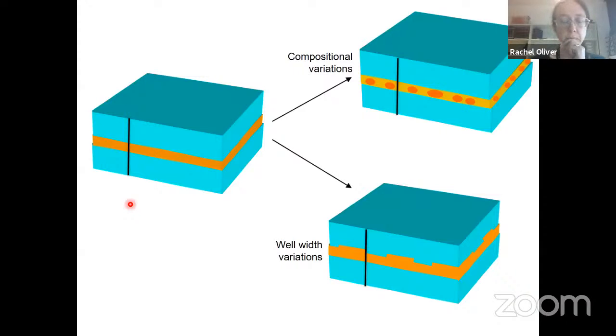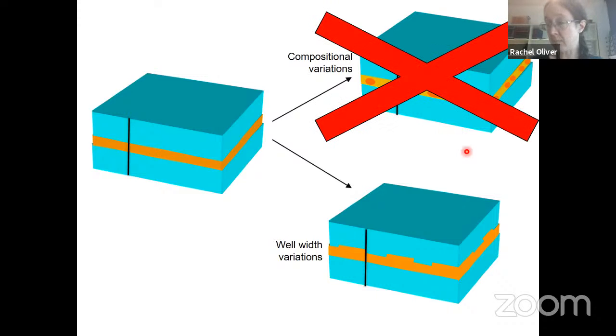Okay, so we started off with a picture where there were defects through our quantum wells, and those defects would cause non-radiative recombination of carriers and spoil the performance of the device. We then said there has to be something going on with the microstructure which stops that. And it could be indium content variation, so these high indium splotches which would localize the electron and hole and prevent them from moving to the defect site. But we've shown that in blue LED materials, they're not there, at least not in the ones that are used commercially. But we've still got this question of the well width variations left. So let's see whether we can find any well width variations in the data, whether the quantum wells have regions that are thicker and thinner.